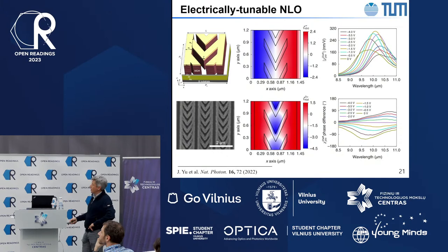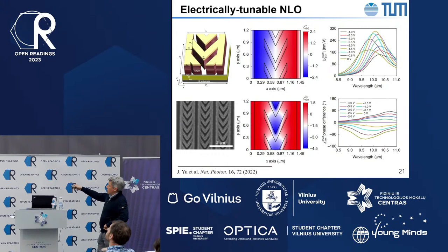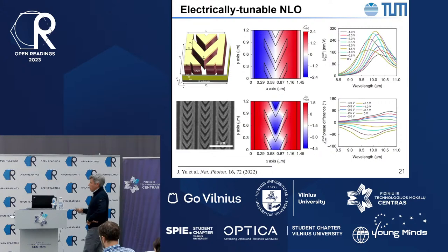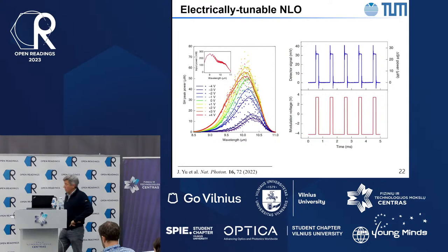And now you can bias your structure with voltage, and you can predict how the chi2 will change as a function of wavelength. So at 0 volts, you expect chi zzz of your metasurface to have this dependence, and at some higher bias voltage, the maximum is going to be there. So if you stay at 9.5 microns, you essentially modulate your nonlinear response from zero to maximum. No nonlinearity, maximum nonlinearity, by just applying voltage. And phase also changes accordingly. So it's not a big phase change, but nevertheless, it changes, let's say, at 9.5 microns by applying different bias voltage. You can change the phase of the response from minus 100 degrees to zero. And you could use it to really demonstrate that you can switch nonlinearity on and off.